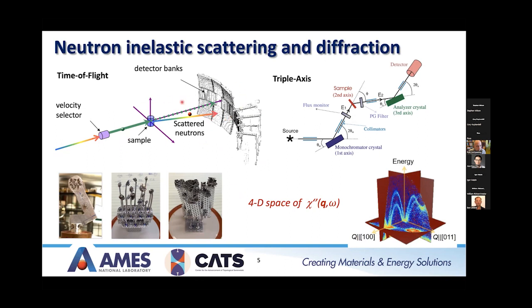For these type of experiments, especially for magnetic inelastic neutron scattering, you need a lot of scatterers because the scattering is so weak. So we typically co-align single crystals into these large arrays, usually just using an in-house X-ray Laue system. The triple axis we use more nowadays for diffraction because you can get very good signal to noise and you can focus in on specific Bragg peaks and look at order parameters.